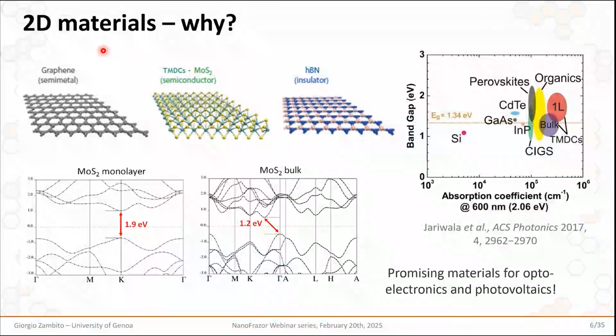Well, these are atomically well-defined materials that present in the form of well-defined atomic layers, and we know plenty of classes of 2D materials. And among these, the one of transition metal dichalcogenides, or TMDs, possess a semiconducting behavior. But also they present optical absorption coefficients that are rather high. And as you can see, they are competitive or even better than more conventional semiconductors, such as silicon, of course, which is the most consolidated and well-known material in the semiconductor manufacturing industry.